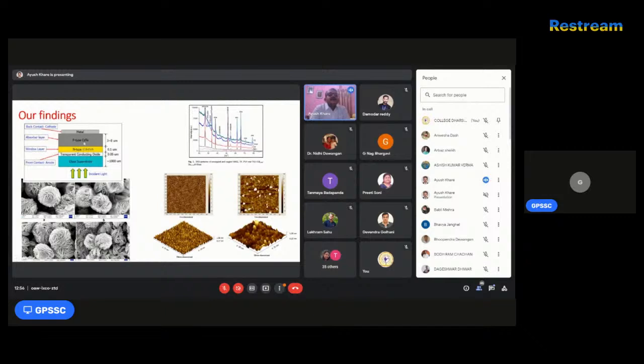So like this is a solar cell that was made using ZnCdS thin film. This is a thin film, yellow film of 0.1 micrometer, not very thin, but it was good. These are beautiful morphologies like flower-like structure, as you can see, layered growth. Since this belongs to CdS material, CdS always grows or crystallizes in layers. So this is a perfect validation of the deposition of CdS in flower-like structure. These are XRD patterns, and this is an AFM image of our sample. See how uniform this is. AFM, atomic force microscopy, helps you to know the surface of your sample, it gives you an idea about how uniform the top surface of your sample is. So this is the outcome of that. This is really uniform, or you can say really smooth.